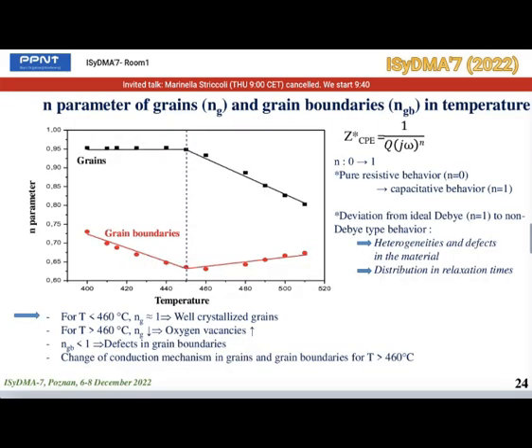The parameter n estimates the deviation from ideal Debye behavior, with n different from 1 indicating non-Debye type behavior, which is due to heterogeneities and defects in the material, causing a distribution in relaxation times. The n parameter value lies between 0 and 1, showing the deviation from a pure resistor behavior to a pure capacitance nature.